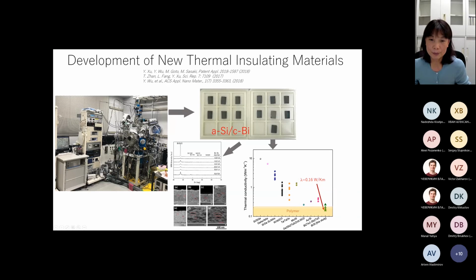And we use our combinatorial sputtering equipment. We synthesized the composite material of silicon and bismuth under different conditions. The X-ray diffraction analysis shows that these materials are composed of amorphous silicon as the matrix and crystalline bismuth as particles dispersed inside it. And depending on our experimental conditions, we can have different grain sizes and different orientations of bismuth. Then we measure the thermal conductivity of this material.